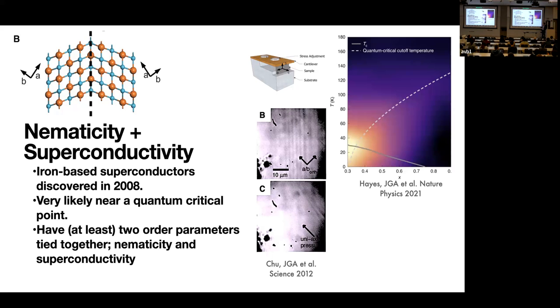And so one of the things that we did more recently is that, once we found a measure of what the internal broken symmetry was, we looked for signatures of it in all sorts of properties, and it looked like they had this quantum critical behavior. In this case, we were measuring a transport property known as the Hall effect as a function of doping and temperature. And if you squint your eyes and think about that diagram that I showed you in the previous slides, it looks a little bit like there's this quantum critical point on top of a superconducting dome. So it looked like that kind of physics was relevant.